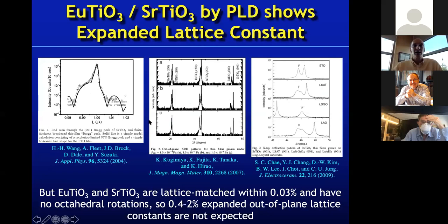So here's, again, evidence that something strange is going on. I showed you first the magnetic properties. I want to show you now the structural properties. So this is a europium titanate film. You're raining europium, titanium, and oxygen atoms down on top of a strontium titanate substrate. And in all three of these groups, in making their films by pulsed laser deposition, what they see is that the film has a different lattice constant than the substrate. Now that's to be expected if this is a mismatched system, but these things are both 3.905 in bulk and with no octahedral rotation. So you go, what's going on here?